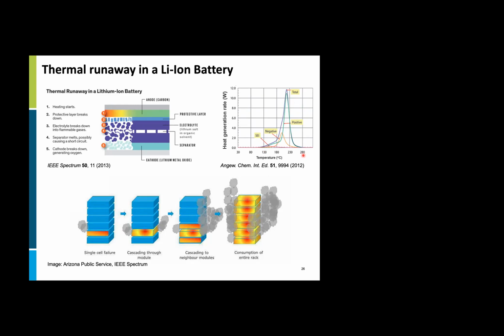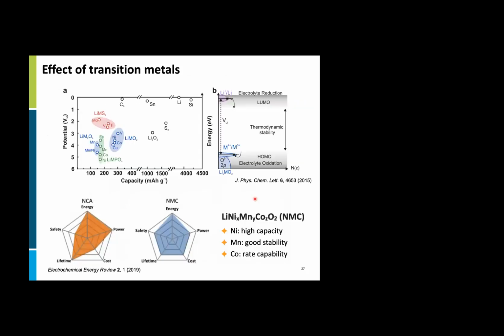And even though the thermal decomposition happens very locally, it can affect the neighbors. So localized analysis is very important. From the in situ heating experiment with charged NCA particles shown before, we can imagine that it would be much better to have alternative cathode materials showing better stability.